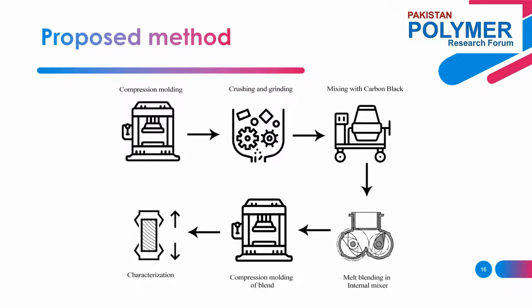After complete drying, the mixture of carbon black and PP powder will be blended in a lab small scale single screw extruder. The resulting extrudate will be size reduced using a shredder and milling machine. The resulting powder will be molded using a lab scale vertical compression molding machine into a square sheet, which will be cut into the specimen for testing purposes.